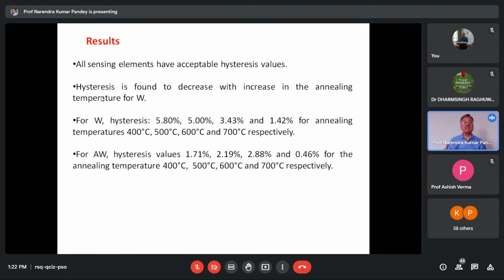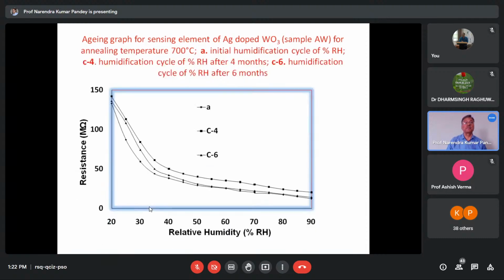Hysteresis is found to decrease with increase in annealing temperature. For WO3, hysteresis decreases 5.8%, 5%, 3.43%, and to 1.4% when the annealing temperature goes from 400 to 700. For Ag doped WO3, hysteresis is small. There is not a definite trend, but certainly the hysteresis has decreased from the values for WO3 to Ag doped WO3. There is a definite decrease in hysteresis when Ag is loaded in WO3.